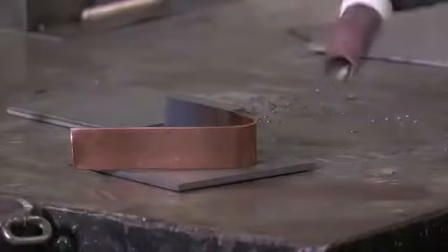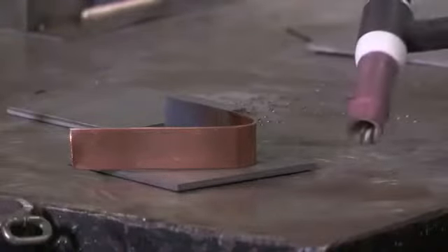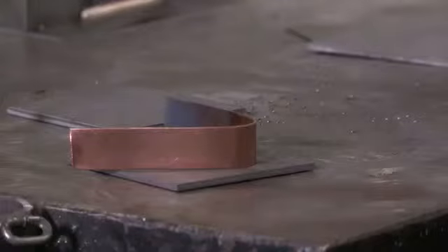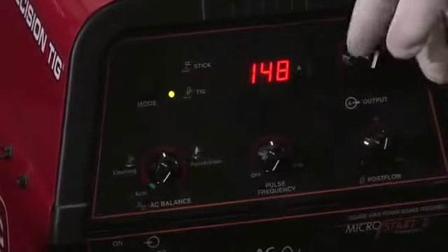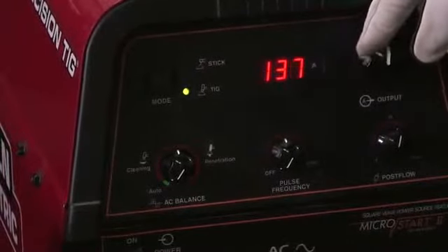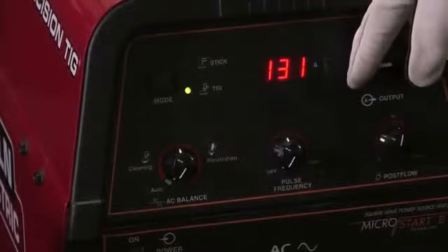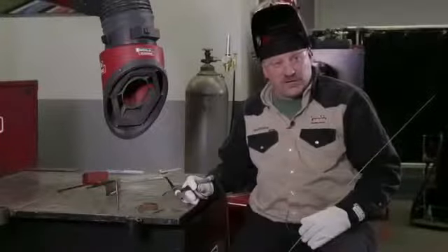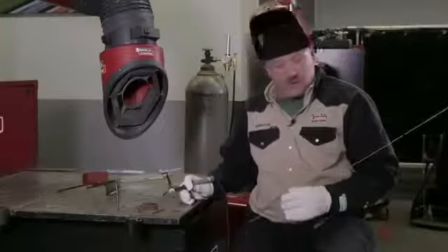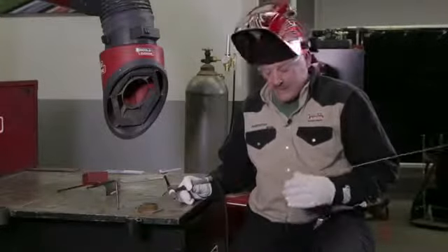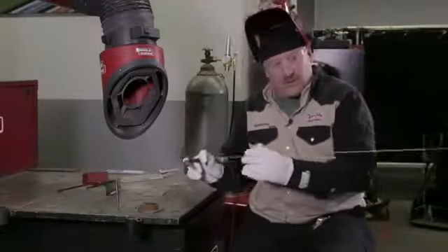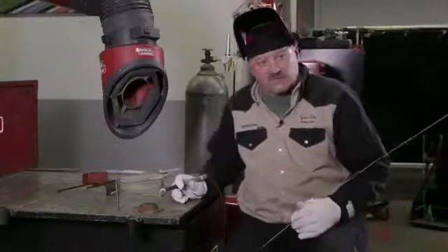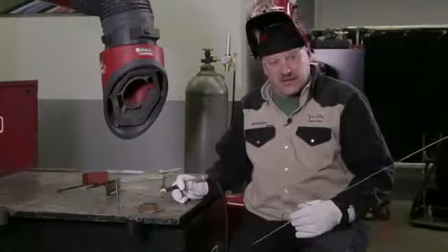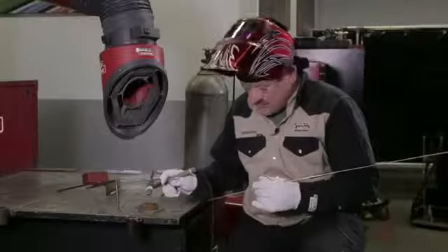I have a little thicker piece of steel here on the bottom. This is about 120 thousandths thick, so I turn my current up some. I'm up about 130 amps. Might not need all that. I'm going to adjust it with my foot pedal, but need a little more current for this thicker steel, and plus that copper is really pulling the heat up too. So I'm going to make this weld, concentrate my heat more on the filler metal, but I want to wet into that base metal. I want to make sure I'm hot enough to tie into that base metal. I'll dab and move.